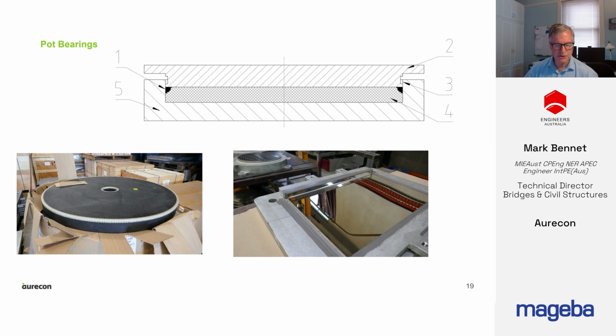Conventional pot bearings have been in use for the last 50 years. They consist of a pot with a rubber disc inside, a piston plate, and there's internal seals. In the past, these internal seals used to be metal rings, and with the millions of cycles of rotation, the metal rings used to wear the sides of the pot, and under high pressure, the rubber can shred and extrude from the pot. So these days, POM chain plastic seals vulcanized into the rubber pad are normally used.